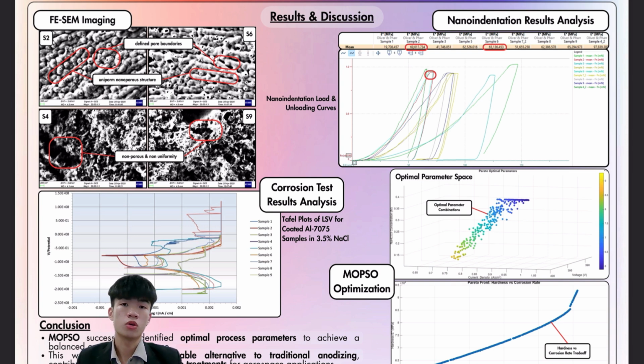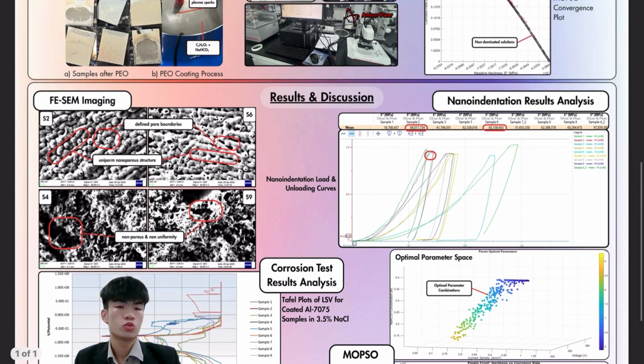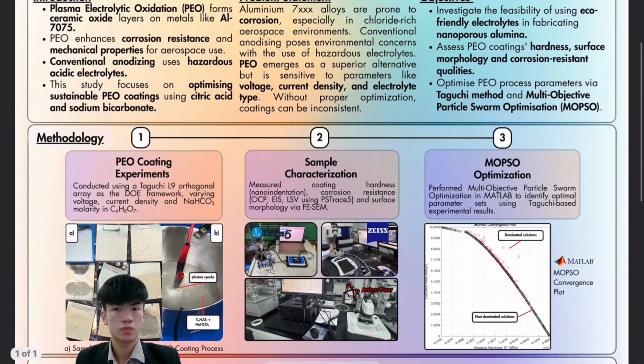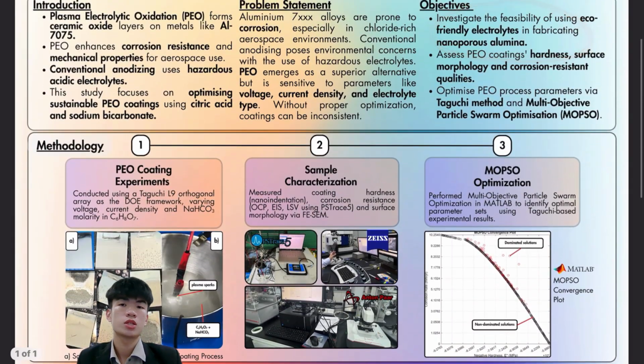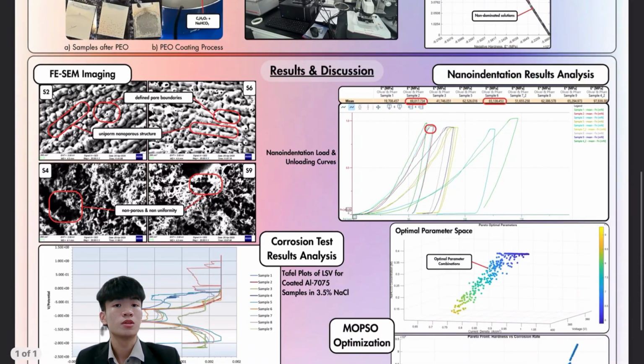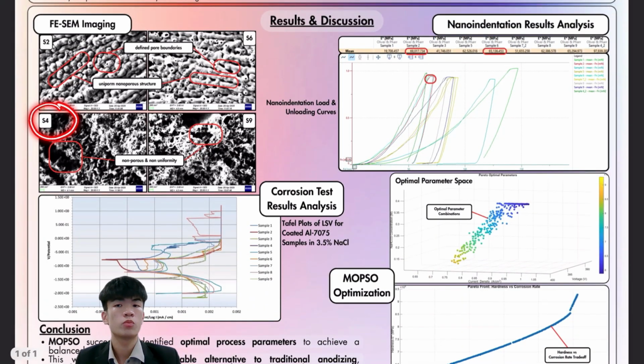Hence, this also confirmed the feasibility of using eco-friendly electrolytes for forming PEO nanoporous alumina coatings, which was the first objective of this research. In contrast, samples 4 and 9 were considered the worst, as they showed non-uniform or defective morphologies, suggesting unstable spark behavior, overheating, or insufficient oxide formation.